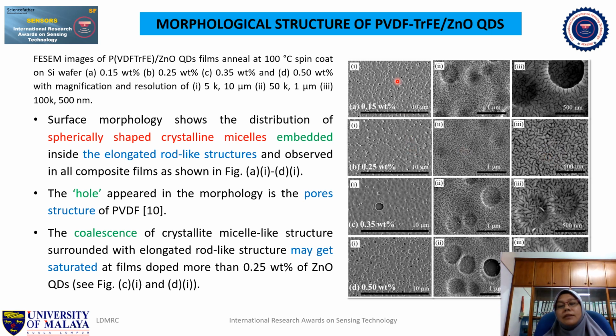So as we increase the composition of zinc oxide, what happened is the spherically shaped crystalline micelle has turned into holes. Okay, so you can see clearly in this figure here. So there is a coalescence between crystalline micelle-like structure with the elongated rod-like structure, and it will get saturated at a certain weight percentage of zinc oxide.